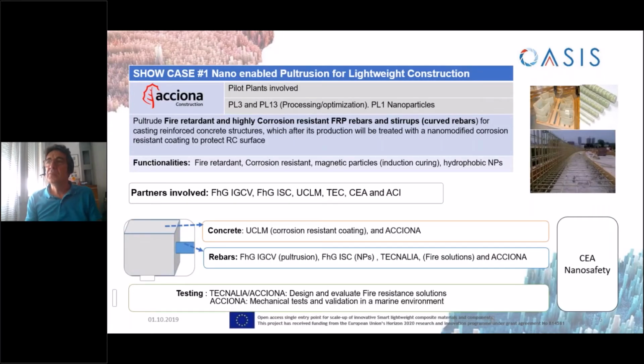So, in OASIS, we propose to develop state-of-the-art multifunctional fiber-reinforced polymer composite rebars with enhanced fire retardant and corrosion-resistant performance. At the same time, we are also interested in optimizing the production. In this case, these rebars are produced by pultrusion, increasing processing speed and minimizing energy consumption, which will have a direct impact on the final cost of the rebars.